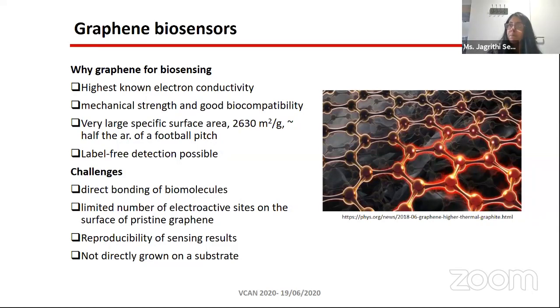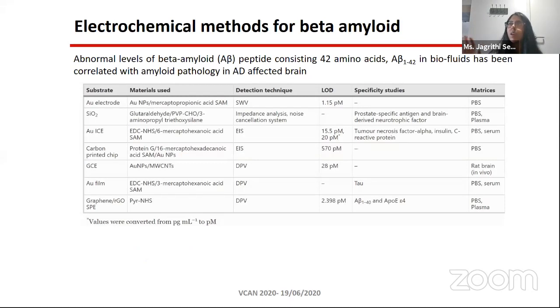This is a small portion of the literature survey that I did for the existing electrochemical methods. As you can see, there are not many. The best biosensors are here, the label-free biosensors, and none of them are based on graphene except for the one that we prepared. The reason, as we already discussed, is that there are a lot of problems with reproducibility and with the attachment of the biomolecules on the sensor surface, and so on.